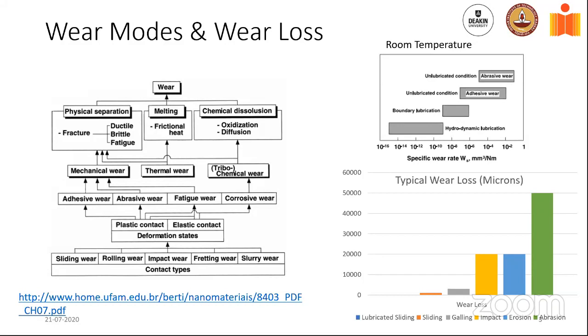Then when the lubricants essentially break down, you start getting into boundary lubrication, and the wear shoots up by a factor of a million. And then when you get into no lubrication and just plain and simple adhesive wear, it shoots up by another 1,000 to 2,000, 10,000. And when you have abrasion thrown in, where something is much harder than the other surface, wear shoots up by another factor of 10. So you can have this huge change in wear, starting from almost negligible to very severe. And you want to keep that in mind, because if you want to see additive manufacturing solve these kinds of problems, you need to start mapping out what the solution space should be in your head.